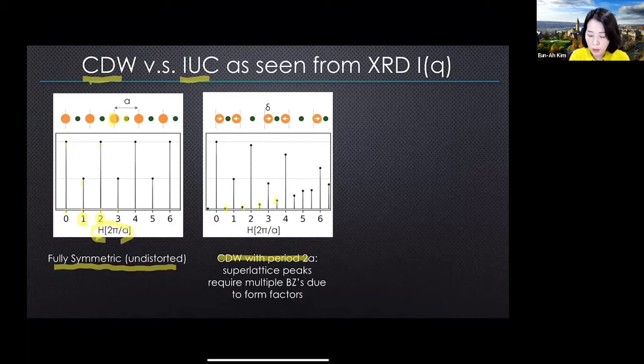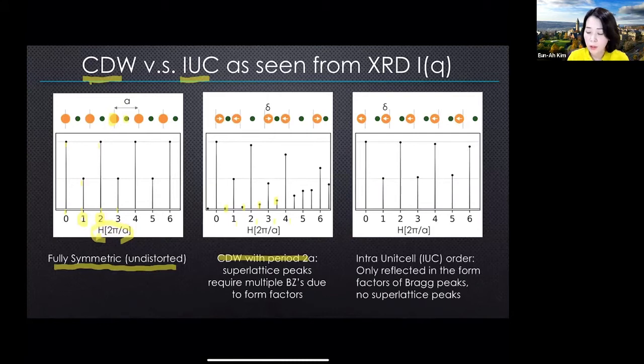But this simulation shows you that not only do you get peaks at the new positions, there is a form factor associated with them, and these are different Brillouin zones. Different Brillouin zones are going to give you different intensities. What I call intra-unit cell order is symmetry breaking that does not change the size of the unit cell. In the previous case, the unit cell was doubled with the charge density wave. With this particular intra-unit cell symmetry breaking, the unit cell size has not changed. However, there is obviously symmetry breaking going on.